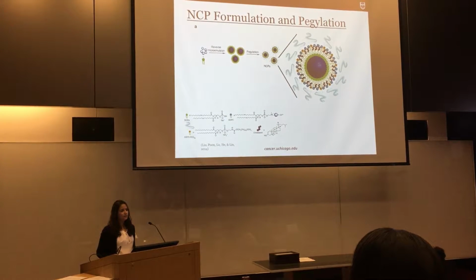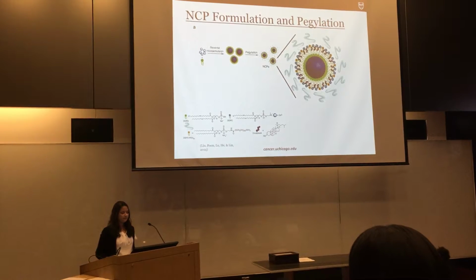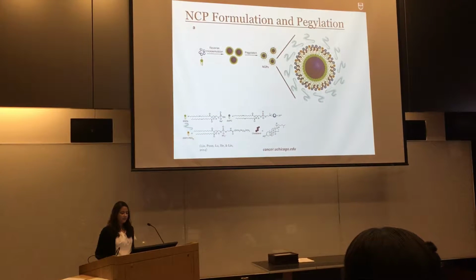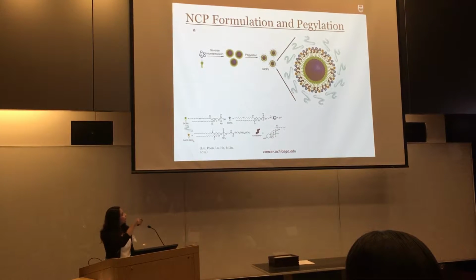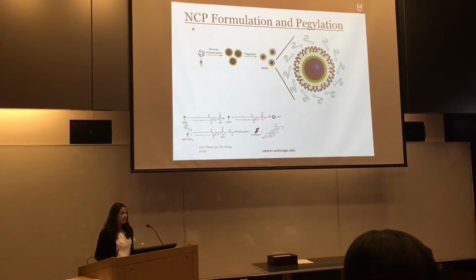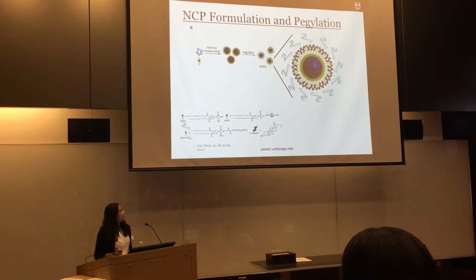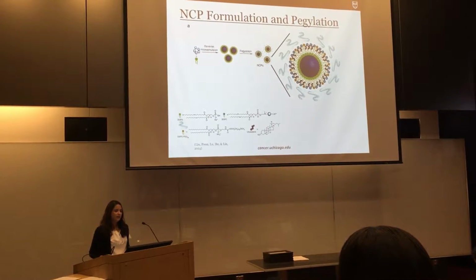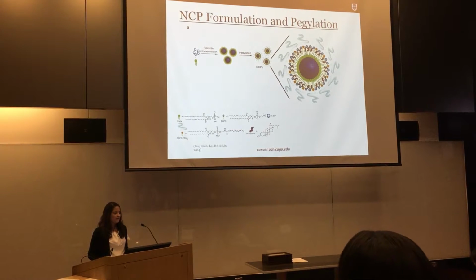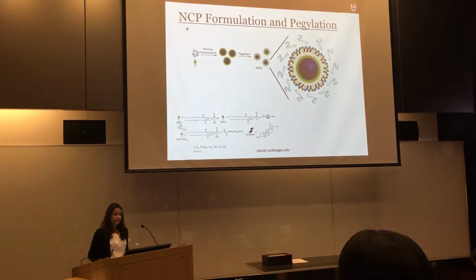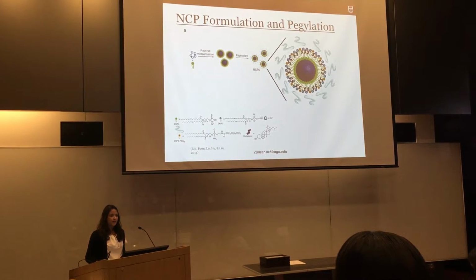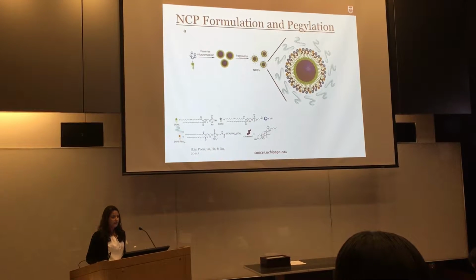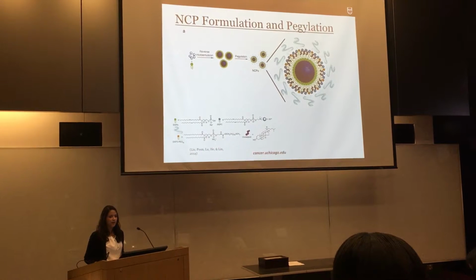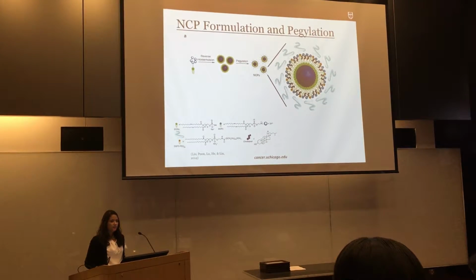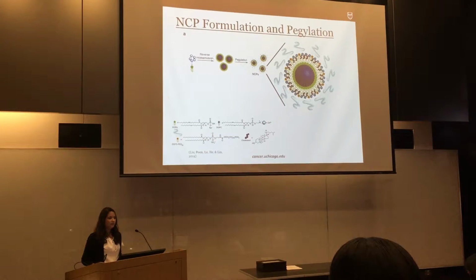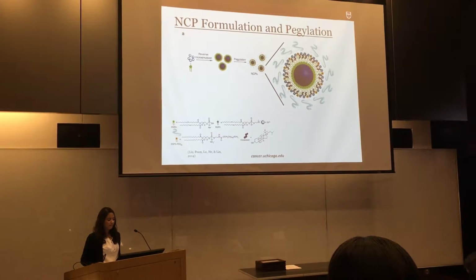Here's the method that was used to formulate the nanoscale coordination polymers. One aliquot of a surfactant was mixed with DOPA, which is here, and to another aliquot of surfactant was added zinc nitrate, which provided zinc ions. These two aliquots were then mixed together and stirred for 30 minutes, and this was then centrifuged three times and resuspended in 20 milliliters of tetrahydrofuran. These particles were then pegylated, again, to provide greater stability and a longer blood circulation time.